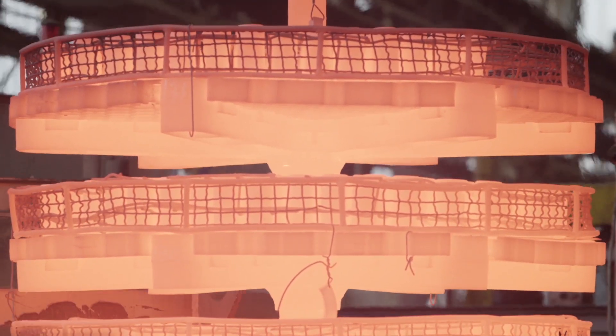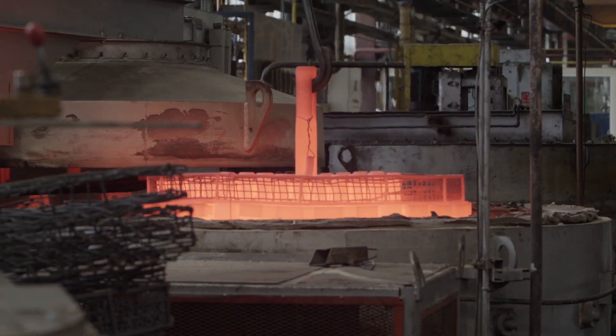We started working on an innovative seamless induction technology that allowed us to take a 2 to 4 week process down to 5 hours.